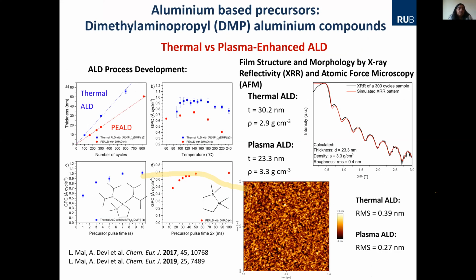Then in this case, we tried the usage of this aluminium DMP precursor, both for thermal and plasma. So the goal was to see whether this precursor just reacts with water to form aluminium oxide, and if we can use plasma to bring down the temperature where we can coat polypropylene or polyethylene terephthalate. So this was the main aim, and we developed a process with water as well as with the plasma.